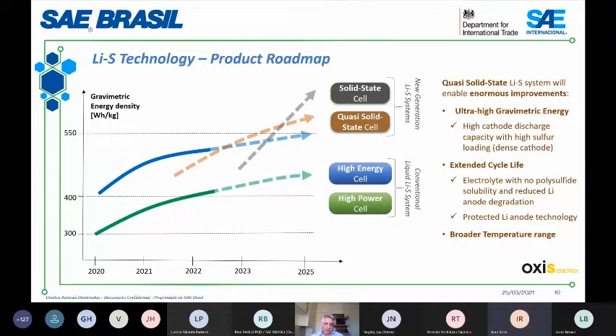So talking about specifics of the quasi-solid state system and its enormous improvement, as I said, the ultra-high gravimetric energy through high cathode discharge capacity with high sulfur loading. So we are talking about a dense cathode. Extended cycle life through a newly formulated electrolyte with no polysulfide solubility and reduced lithium anode degradation, and protected lithium anode technology. All of them are patented technology. And also we will have a broader temperature range. So it will be effectively an enormous improvement for our technology for the application of our customers.